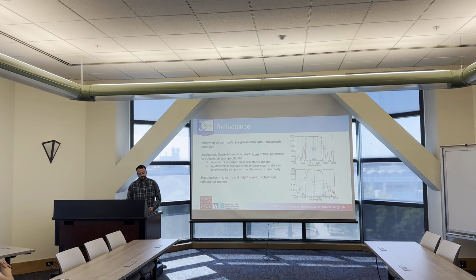So a little bit more about reflectance. This is performed on every wafer, on the as-grown structure throughout the full growth campaign. We extract important characteristics from each spectrum. The cavity mode wavelength, which is the dip in the stop band. We get the stop band width and center, and see how the center aligns with the cavity mode wavelength. The stop band height as well, which is uncalibrated but can be used to assess variations in the mirror reflectivity across individual wafers. But the most important is the cavity mode wavelength, which determines the emission wavelength of the VCSEL, and this is determined itself by the composition and thickness of the inner cavity layers.